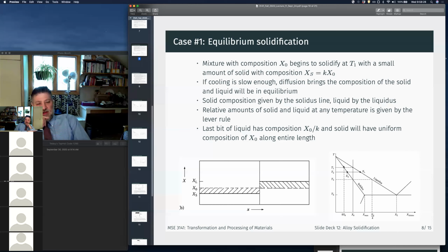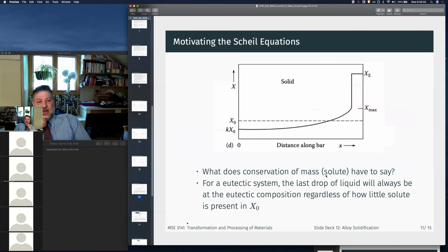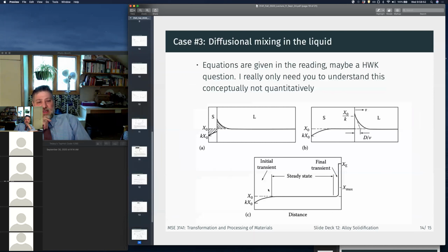we start out here on our liquidus, we're going to pile up really quickly in front of that interface until we reach this point here. And when we reach this point here, composition in our liquid, local equilibrium states that our solid composition should be X naught, right? And essentially this is where we hit a balance. We hit a steady state.